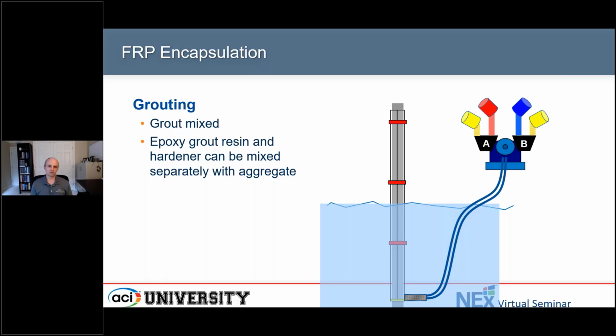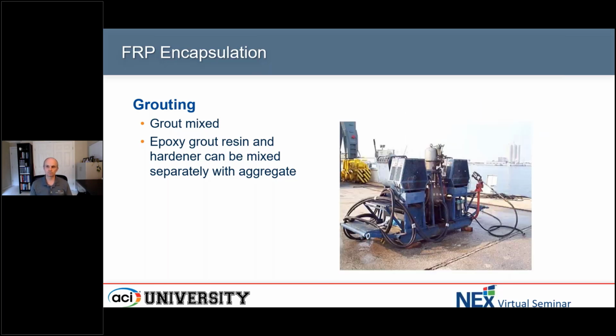These are typically either a cementitious grout or an epoxy grout. The epoxy grouts, sometimes you'll see the resin and the hardener of the grout mixed separately, each of those components mixed separately with sand, and then they're pumped separately and actually mixed right before they are pumped into this encapsulation.